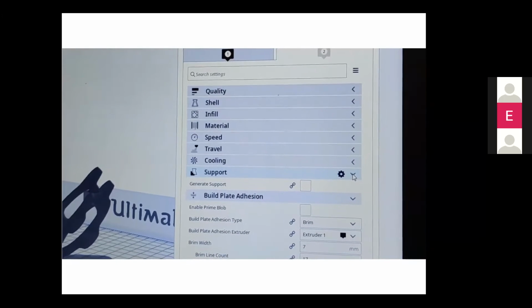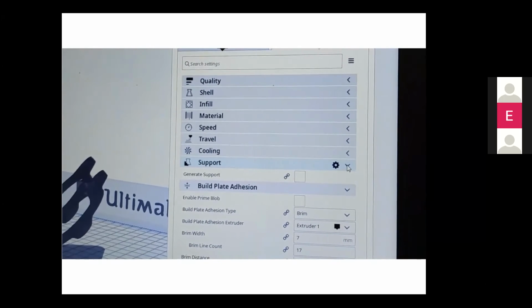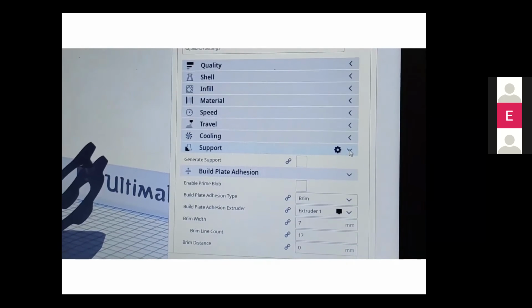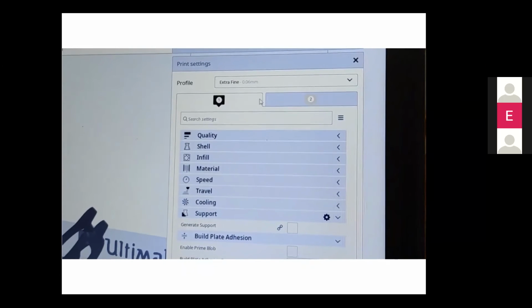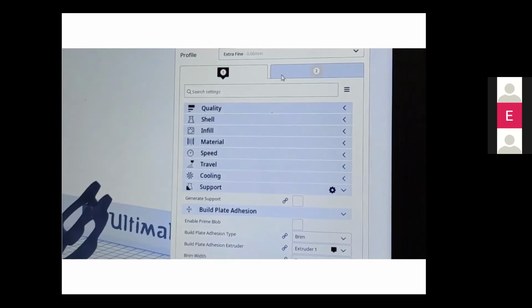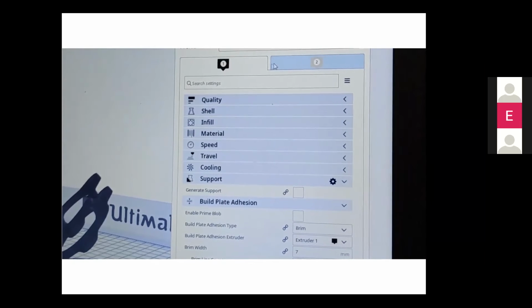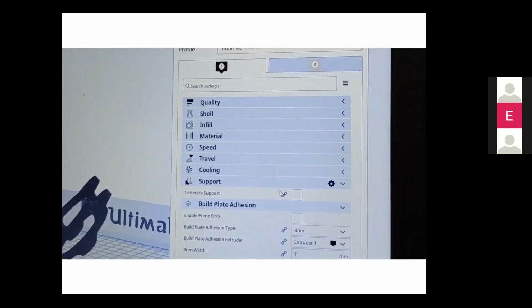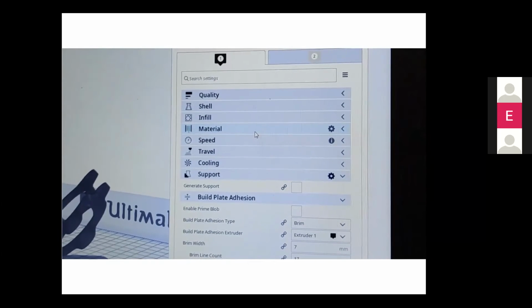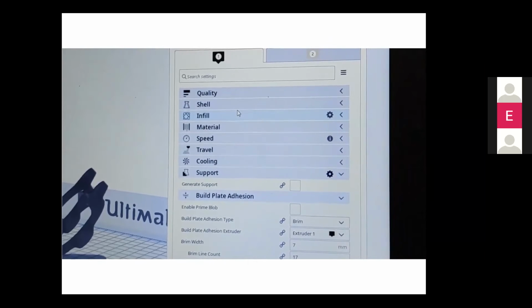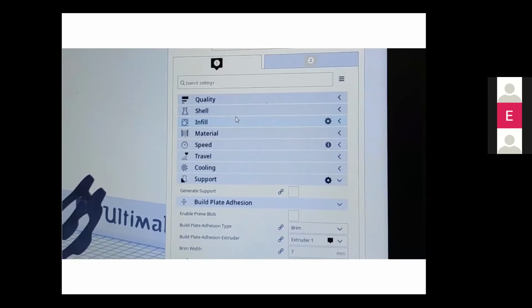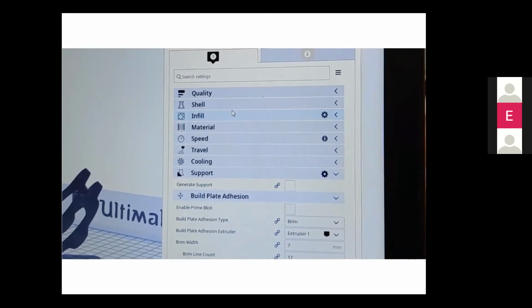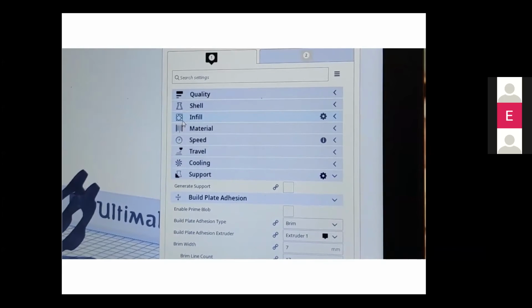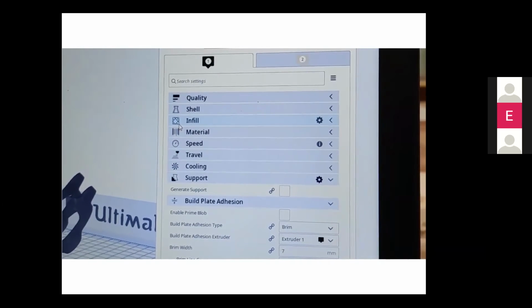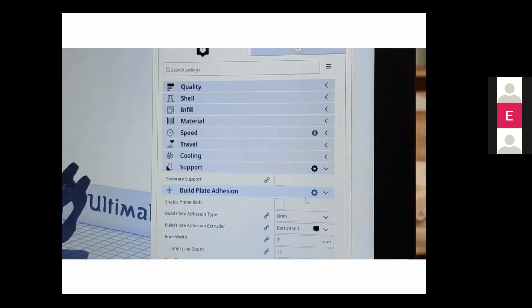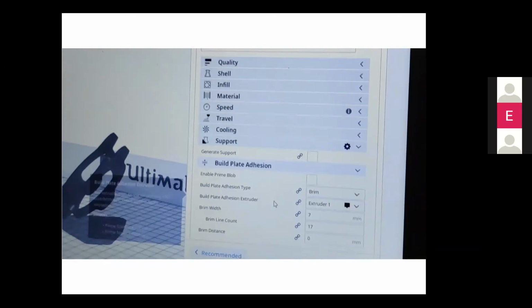After printing, you have to keep the part in water of 50 degrees centigrade, where the PVA material will melt out and you get the actual part out. So be sure which material is in which extruder, and which core is in which extruder. Make sure you have the BB core in the second extruder and the AA core in the first extruder. You have to give the same settings and parameters in this Cura software as match the hardware components like extruder or material. These two play a very crucial role. Do not give PLA material in the software and then put ABS material in the printer. That may damage the printer and there is also a chance of clogging of the core. So this is how the support concept works and how the hardware component works.